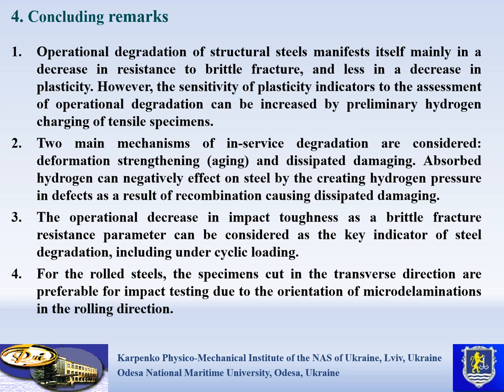Absorbed hydrogen can negatively affect steel by creating hydrogen pressure in defects as a result of recombination, causing dissipated damage. The operational decrease in impact toughness as a brittle fracture resistance parameter can be considered as the key indicator of steel degradation, including under cyclic loading. For the rolled steels, specimens cut in the transverse direction are preferable for impact testing due to the orientation of micro-delamination in the rolling direction.